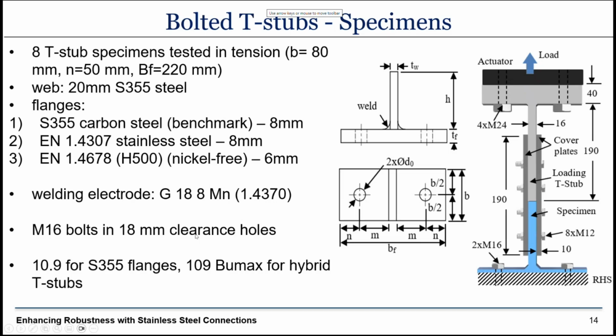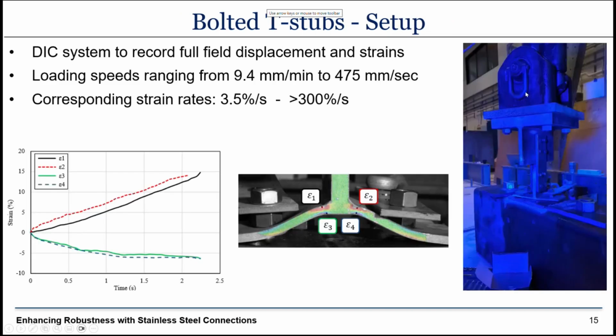So we tested in tension under both static and high strain rates. Here you can see the overall configuration that we used. The blue is the specimen we tested, and we connected that to the actuator and we applied tensile load. We used digital image correlation to record full field displacement and strains. The loading speeds in this case were increased from what we did before.